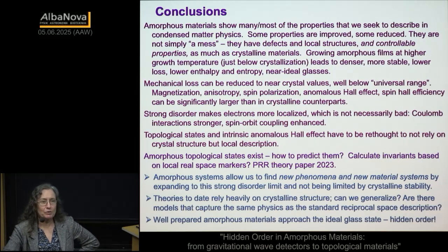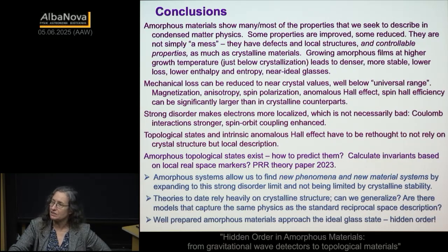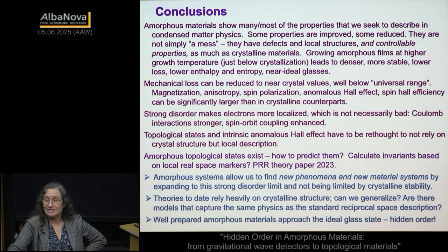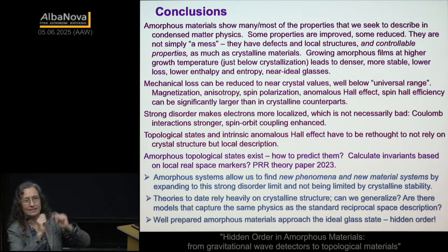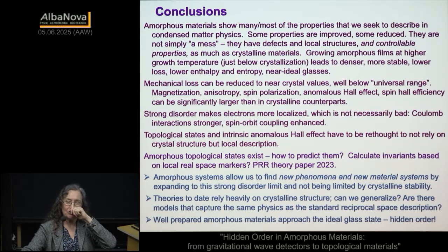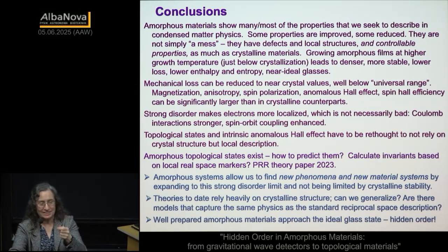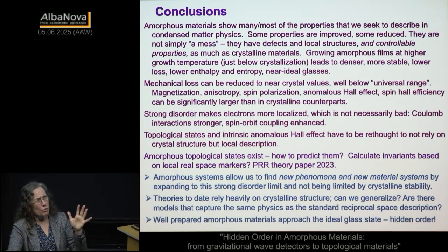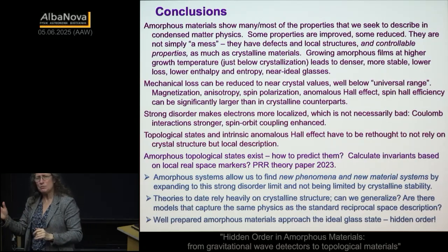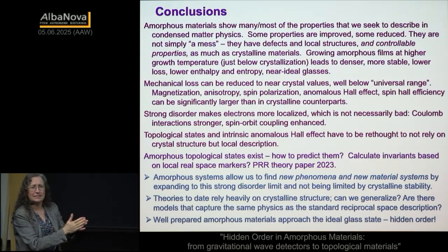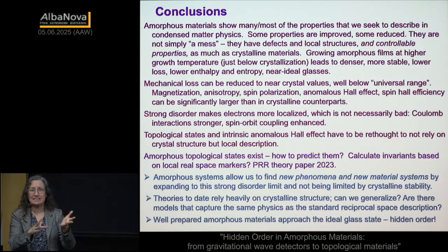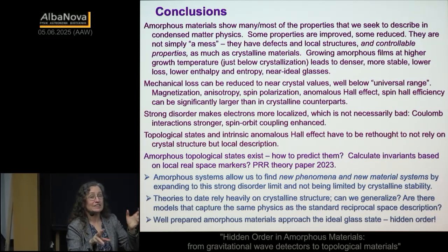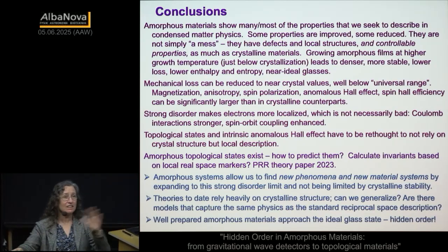And by the way, to add a further weirdness from a technology standpoint, the way you get rid of these dangling bonds is you put hydrogen in. That sounds fine. Hydrogen's a proton. It can go around, find that dangling bond. But in really classic amorphous silicon, it's anywhere from 1%, which sometimes is enough, but usually it's more like 10%. So why in the world do I need 10% hydrogen to get rid of a part in 10 to the 4 of dangling bonds? What are all the other hydrogens even doing in there? And there is no answer, and nobody worries about it. In technology, they just do it.